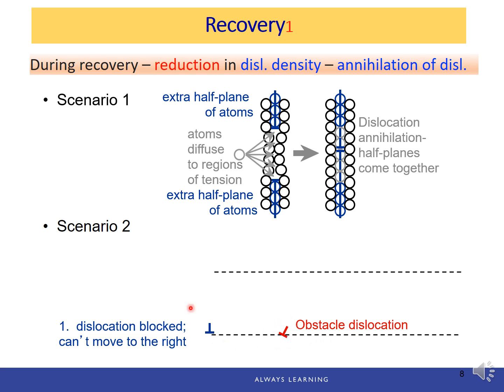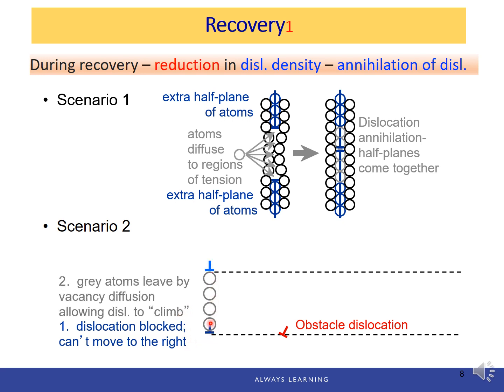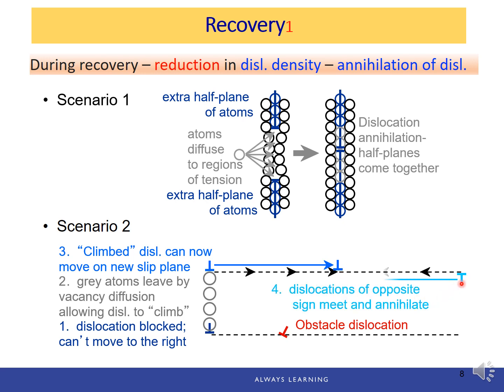Now, again, because of the elevated temperature, the atoms diffuse by vacancy diffusion. So it looks like this dislocation now climbs up to another slip plane. So it can slip to the right without obstacles. So dislocations of the opposite sign will meet the other dislocation and annihilate. So again, both dislocations will disappear.